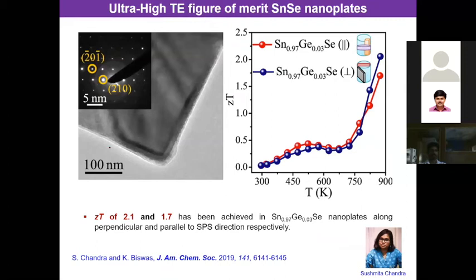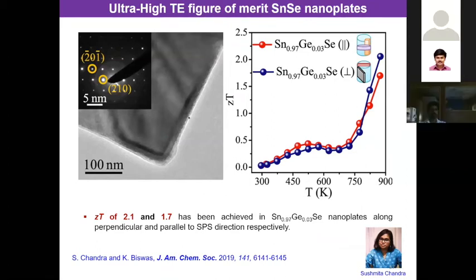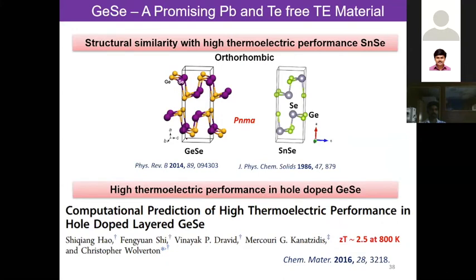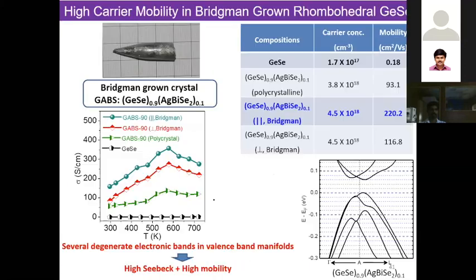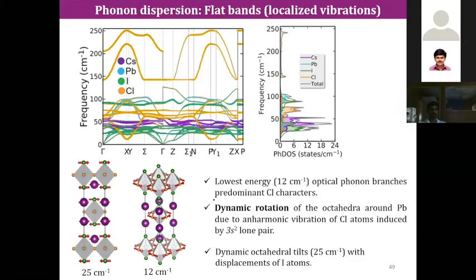And then you see this nanoplate, and with this nanostructure, basically nanoplate, which has significant bond anharmonicity and lattice anharmonicity, we get a ZT of above 2, and this is one of the highest in simple nanoparticles or nanoplates, which was done by my student Sushmita. And with that, I'll complete the talk because we are almost at the time. I'll not exceed the time here, and then we'll have more questions. So let me skip all these things and come to the conclusion.